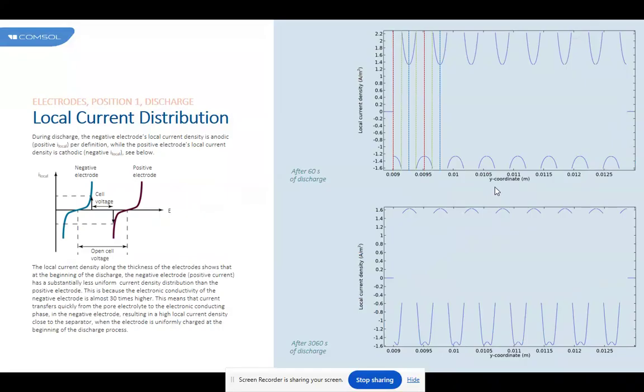This is because the electronic conductivity of the negative electrode is almost 30 times higher. This means that current transfers quickly from the pore electrolyte to the electronic conducting phase in the negative electrode, resulting in a high local current density close to the separator when the electrode is uniformly charged at the beginning of the discharge process.